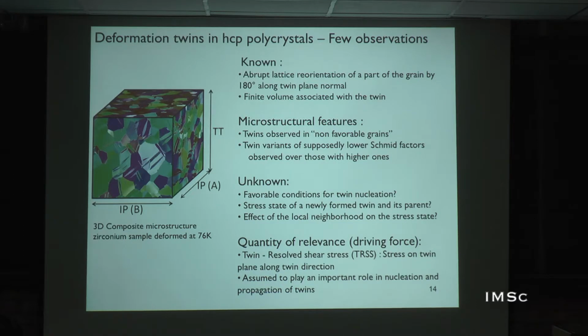I do not have that level of knowledge to comment on that, but one thing at least I understand is if you want to trust the molecular dynamic simulations about these physical phenomena, one of the important parameters is predicting what is called the stacking fault energy, and that means your underlying potential needs to be substantially rigorous, because a lot of this process, while I am smearing it out, essentially depends on the dislocation reactions and their interactions, and you can only do a good job if your potential is able to do a good stacking fault thing.